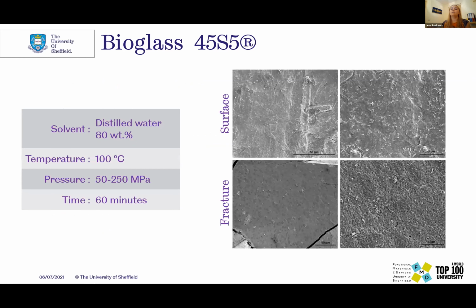So I used distilled water as the solvent at a much higher volume than we would normally see in cold sintering, 80 wt.%, and then pressed it between 50 and 250 megapascals for 60 minutes at just 100 degrees. And you can see on the SEM images that we've got there, the top surface and the cut through fracture surface. And it's really quite dense, and there's some areas in the fracture surface that look a little bit denser, but that's from the original powder.